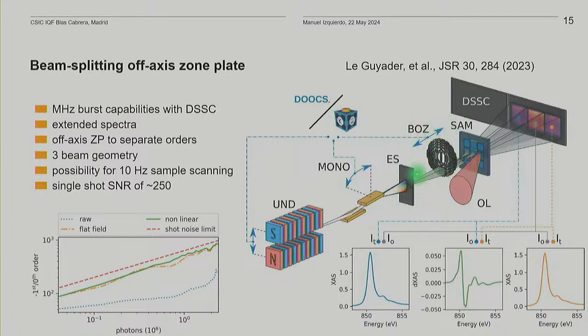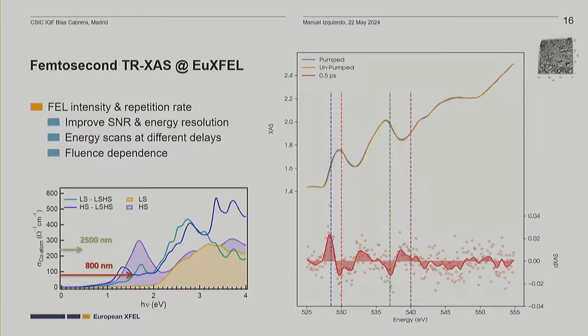So basically what you do is you make your sample in membranes, and you use this element that is the grating and a focusing element, and then this passes through these three membranes, and then you measure 3 images in a fast detector, DSSC. In principle one should be empty to have an I0 reference, the other one should be with no laser to have the static or unpumped, and the others should be with laser to have the pump. And from there, by doing combinations, you are able to calculate the different spectra with a signal-to-noise ratio that approaches very much the shot noise limit. You can see here the shot noise limit results and what we can achieve. So when you do this, you see that there is an advantage of free electron lasers.